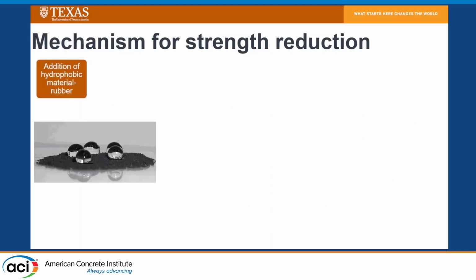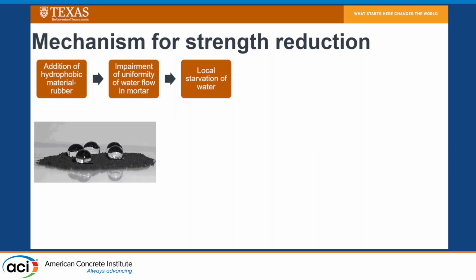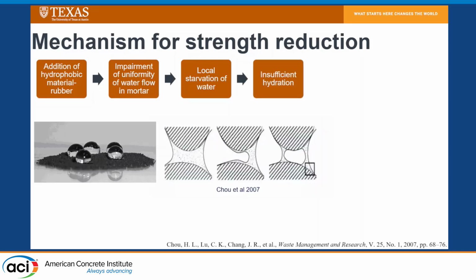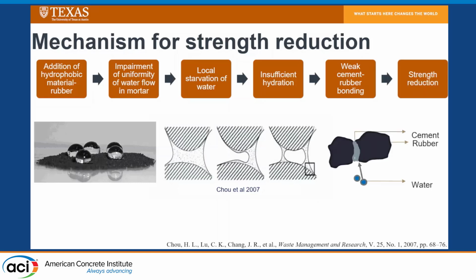With respect to the reason why this is occurring, one of the things to note is that tires are going to be very hydrophobic. And this impairs the flow of water in your mortar or in your cementitious matrix. The result is that this is going to cause a local starvation at the interface where you have your rubber and your cement. And this is essentially going to lead to insufficient hydration. So instead of an increase in compressive strength, you get a reduction in hydration kinetics because you're not having good bonding between your cement and your rubber. And the end result is that you're going to have a strength reduction.